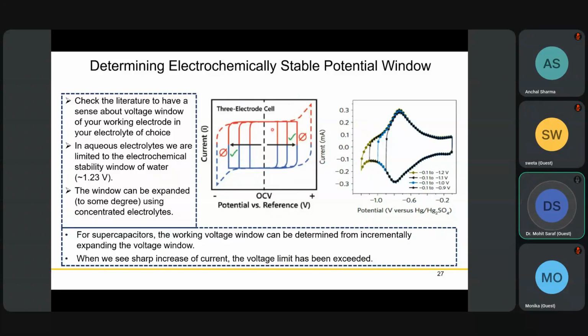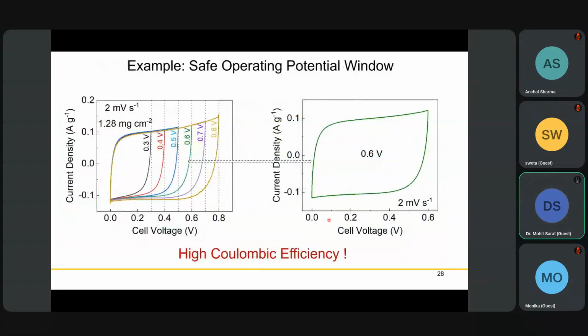When you perform the cycling test, basically the cycle life will be very poor, because you are inducing unnecessary side reactions which will kill your cell faster than in the normal mode. So it is very important to determine your stable electrochemical potential window. In this example, it is clearly shown that if you go beyond this point, the sharp tail increases, so you should cut your potential at this point.